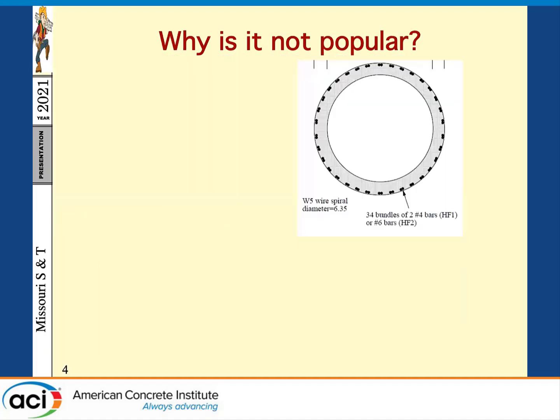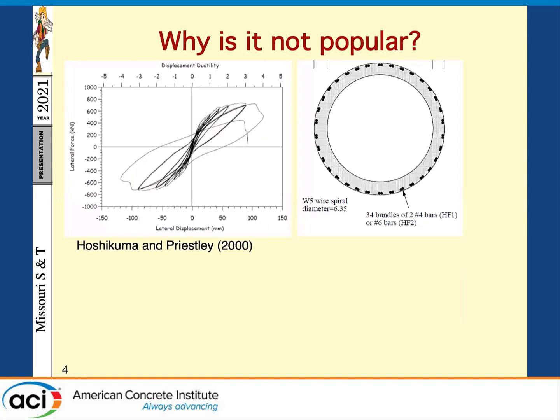There has been some research at the University of California, San Diego, where they moved the reinforcement from the middle of the concrete wall to the outer side, which improved the ductility. However, it is still a limited displacement ductility. They reached a displacement ductility of roughly 3.5, which is not adequate for high seismic regions. So this is why hollow core columns are not very popular. It's not something new, but it's not very popular because of the lack of ductility.